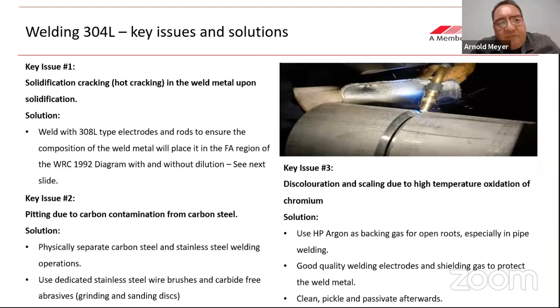Now, if we look at 304L, that is probably the stainless steel that is used the most all over the world. It is a versatile material. It's got its limitations, but it's a very good material. The key issue there, the number one, and that's true for all austenitics, and the most important one, is solidification cracking of the weld metal upon solidification.